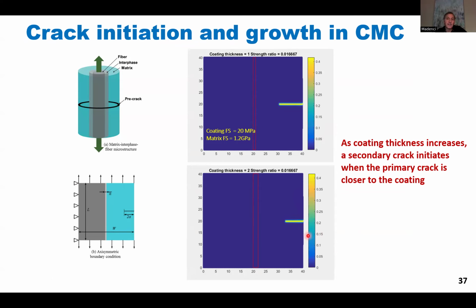The idea here is, what is the effect of, for example, the interface strength or the interface thickness? Okay, so the coating thickness here is 1, and here the coating thickness is 2. So you can see the effect of interface thickness. In this case, the crack initiates as the main crack gets closer to the coating here. Okay. In peridynamics, as I mentioned before, we don't have to worry about singularities because we don't take any derivatives. So there's no mathematical singularity.